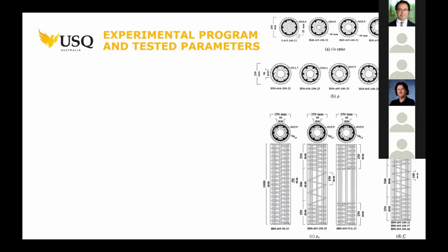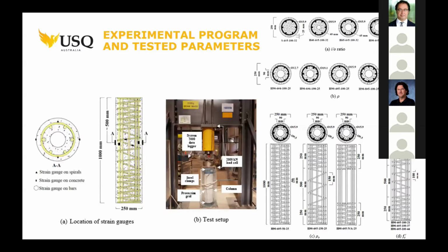We have designed the experiment based on that. We selected a range of inner to outer diameter ratios, different longitudinal reinforcement ratios, and different lateral reinforcement ratios by changing the spacing between lateral reinforcement. And we selected 4 ranges of concrete strength within the normal range of concrete, and tested that under pure compression until failure, using the instrumentation that all of us know, which is strain gauges and LVDTs.